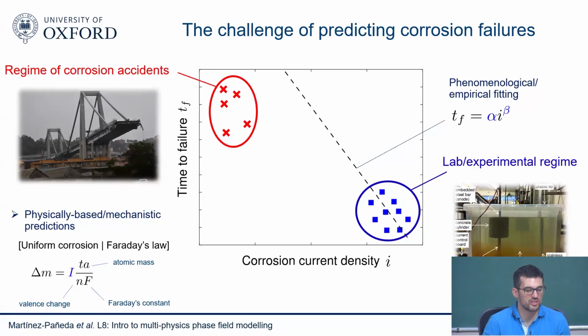The problem is that, of course, these failures do not occur due to uniform corrosion. They occur due to localized corrosion, and localized corrosion is a much more complicated problem. But this points in the right direction. This is what we need to do. Maybe it won't be a closed form solution, and I guess that's part of the problem, that in order to predict corrosion, it's not as simple as coming up with a closed form solution. Experiments alone are not all that you need; you need advanced computational modeling to be able to incorporate all the physics, because localized corrosion is much more complicated than this kind of 1D corrosion.